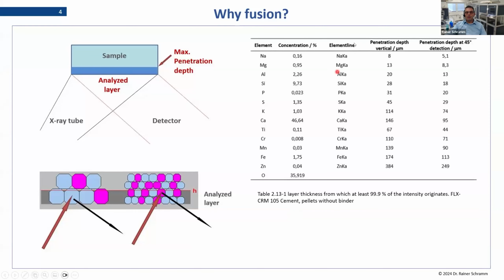For that, I put this table here from a cement sample, and the elements here are in the order of the penetration depth. That means the lightest element, sodium, is on top, and there we have a penetration of just 8 micrometers. While if we go to heavier elements like iron, we already have a penetration of 174 micrometers. If we think about that, the typical sample we grind in a disc grinder comes out between 50 and 100 micrometer particle size. This means that here we just touch the downside in the measurement, while for iron we measure at least 3 layers of particles.